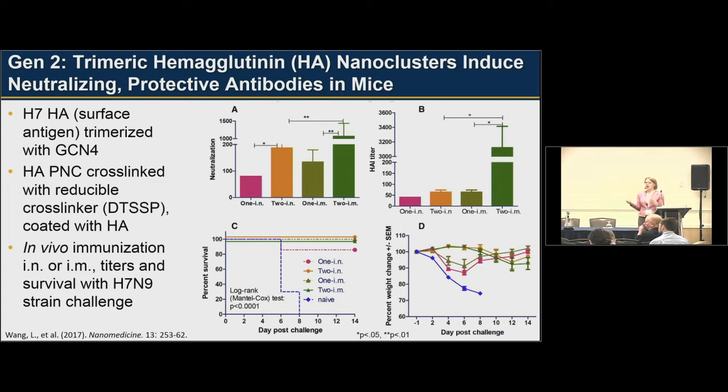And so one of the things that is not talked about a lot but is really important is that when you put nanomaterials in the body, proteins from the blood or the interstitial fluids or wherever it is, the lungs, proteins from the surrounding solution coat particles immediately. And so now you have something that is coated with the body's own proteins, which significantly affects the immune response. And so what we can do to preempt that a little bit is make our own protein coating. And so by pre-coating with hemagglutinin, we know that we have now a surface of properly folded hemagglutinin on the surface, and that may reduce the adsorption of other proteins from the body, which are not going to be helpful and may mask our particle.